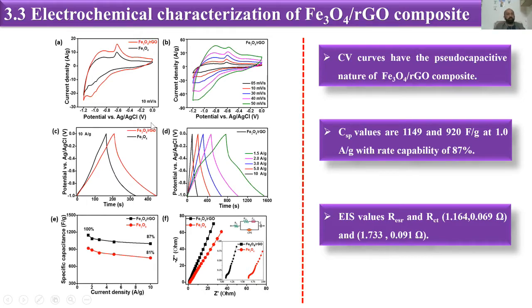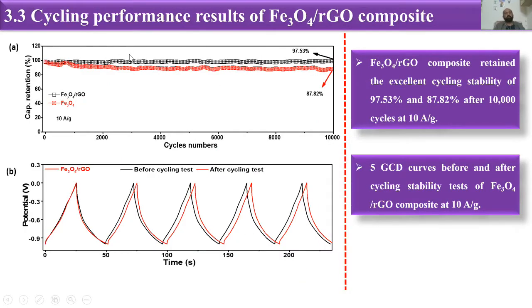Then again, we have done the cyclic performance to check the stability of our materials, how stable our material is if we increase the number of cycles. So we have seen the stability of our system was quite remarkable, about 97 percent for this one and 87 for the iron oxide. And again, we have tested the cyclic curves before and after the cycling test, and we have again got the regular pattern after this number of cycles.